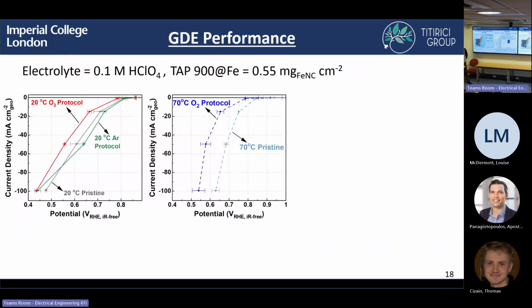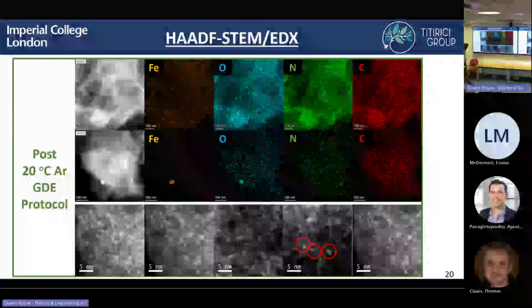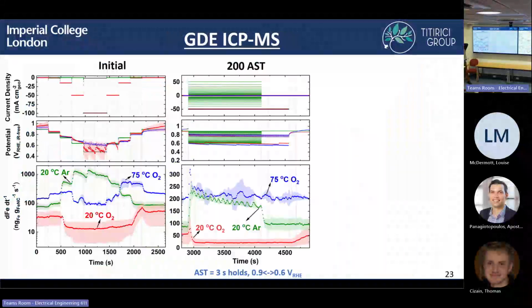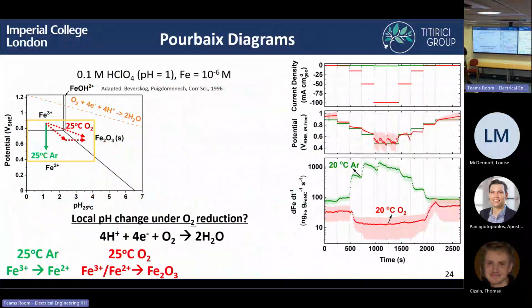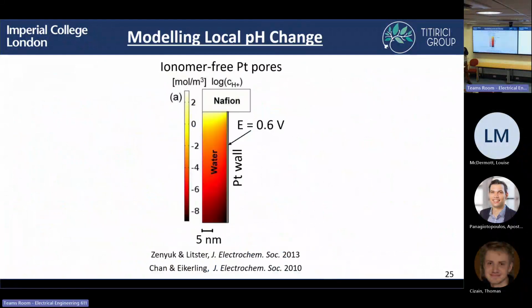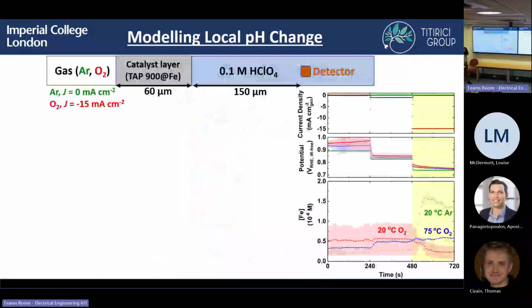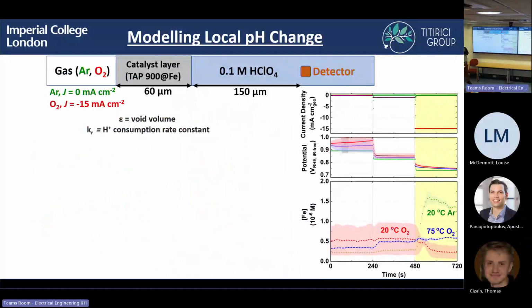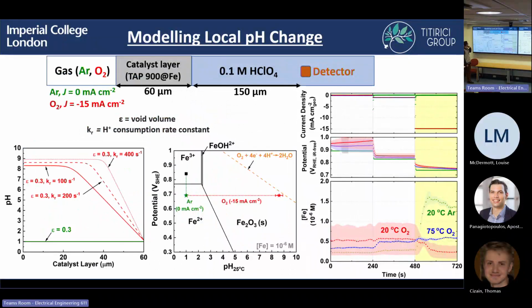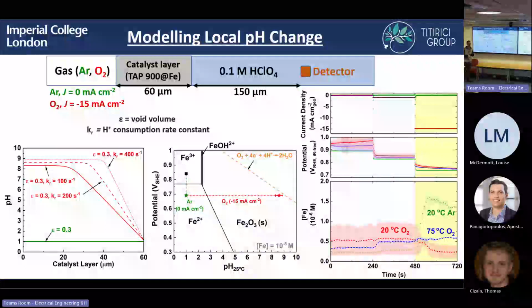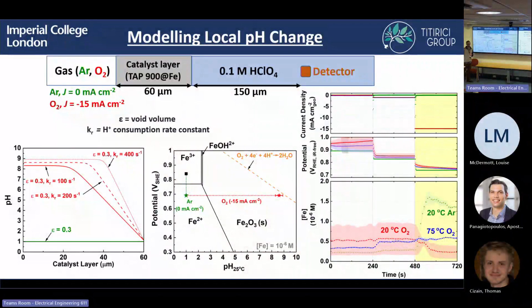We saw when we changed the void volume, the epsilon, in the microkinetic modeling, it has an effect, but still you end up with the same sort of result. Here I don't show the different epsilons, I just show different proton consumption. But if you have a different epsilon, which is your void volume, that would change if you have a different amount of mesopores, for example.